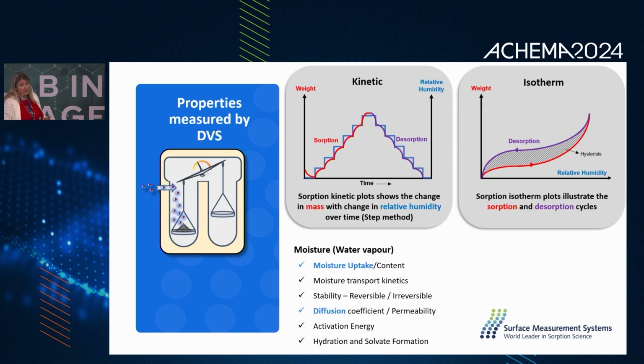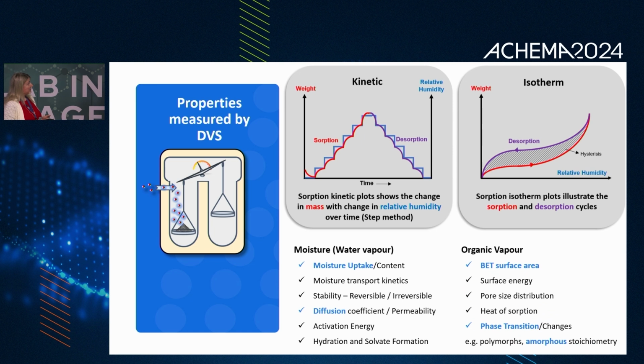So you can look at the moisture uptake. You can look at the moisture transport kinetics. You can see how stable your material is. You can do diffusion, permeability, activation energy, hydration, and solvate formation as well. By using organic vapors, you can determine the BET surface area, and you can use octane instead of nitrogen or krypton. It is a non-destructive technique. Also surface energy, pore size distribution, heat absorption, and also phase transitions, for example, polymorphs, amorphous content, stoichiometry as well.